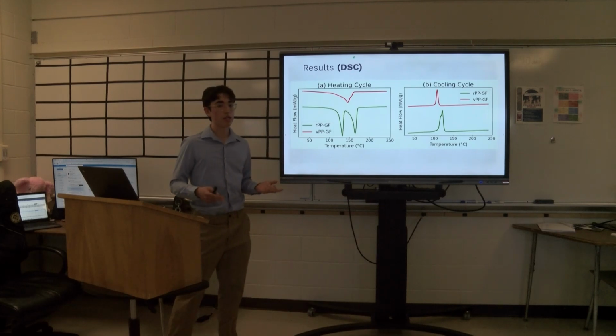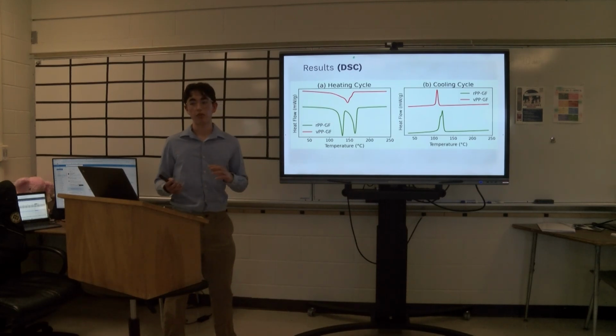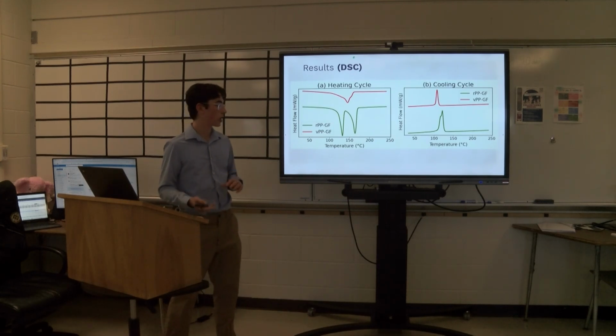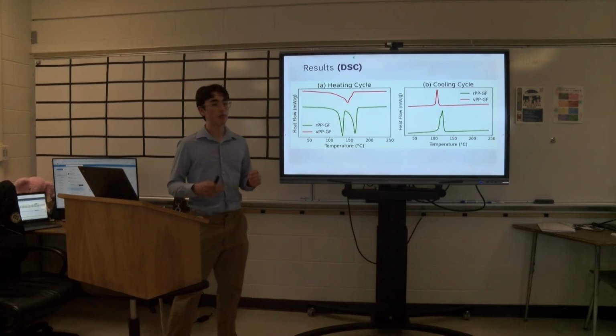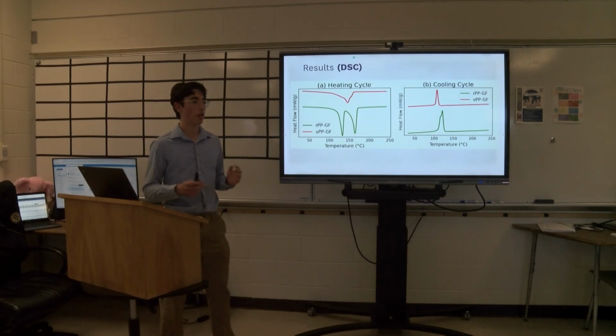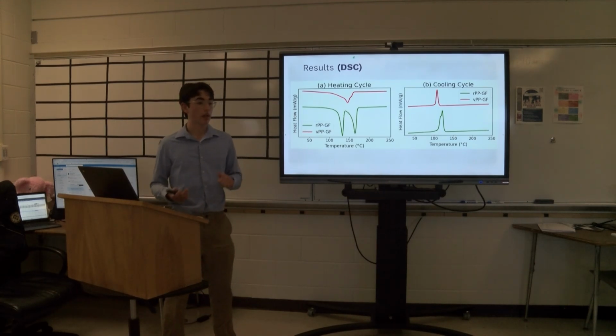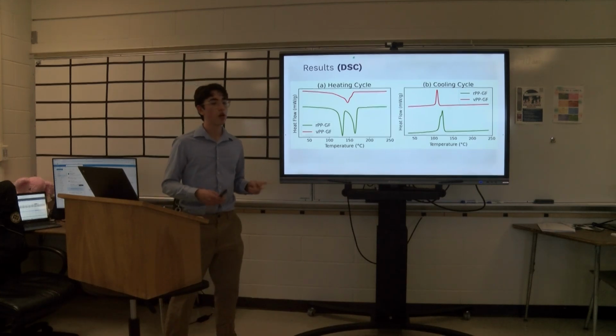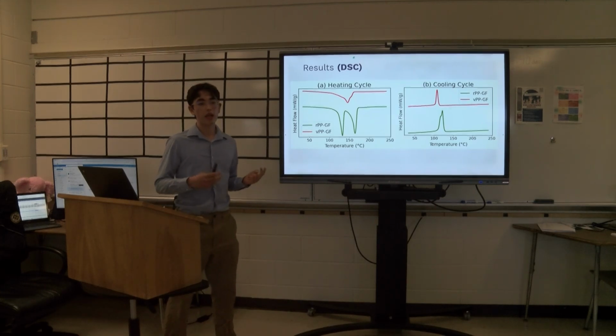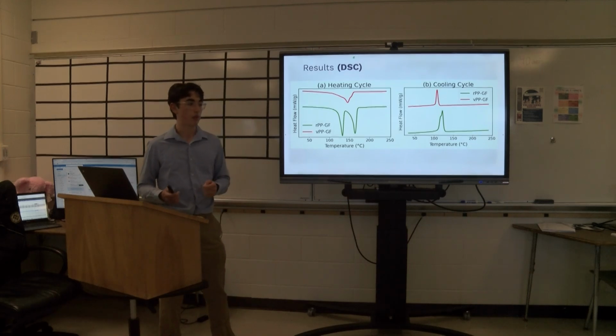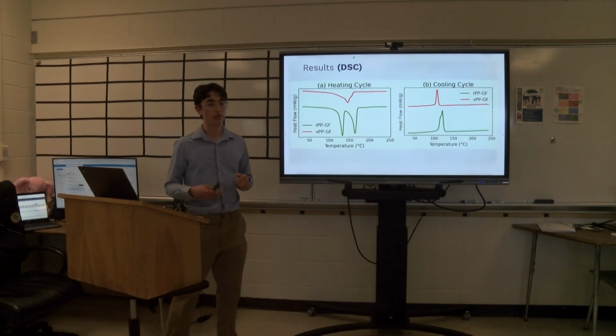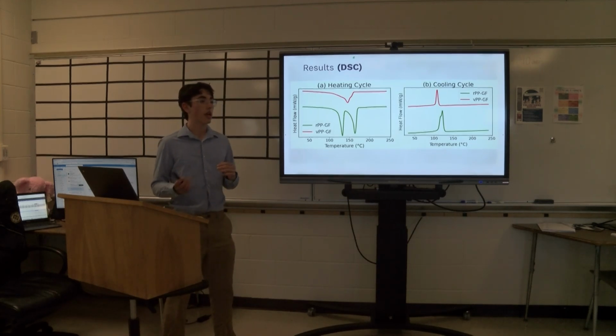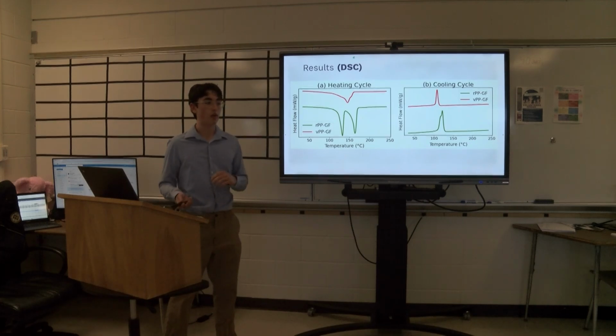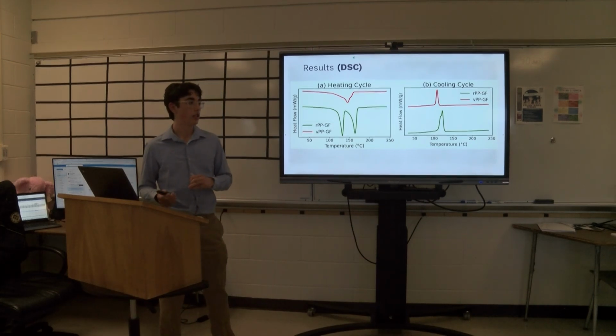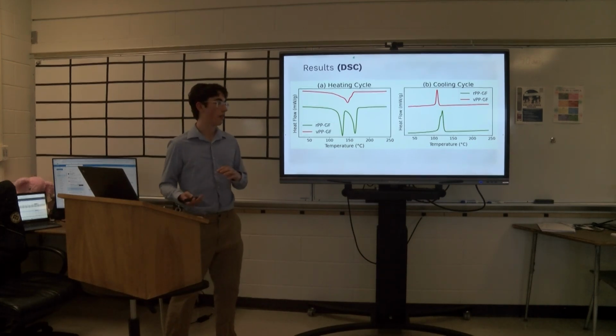I assumed the second peak to be polypropylene because it was similar to other values I saw in the literature. And the first peak I assumed to be high density polyethylene for a couple of reasons. Number one, at a very similar value to others that I saw in the literature. And two, we already know from earlier that high-density polyethylene is present in ocean plastic and is present in fish and rope. So it seems that was likely, if it wasn't intentional, inadequate filtering led to the addition of residual HDPE in the final product.